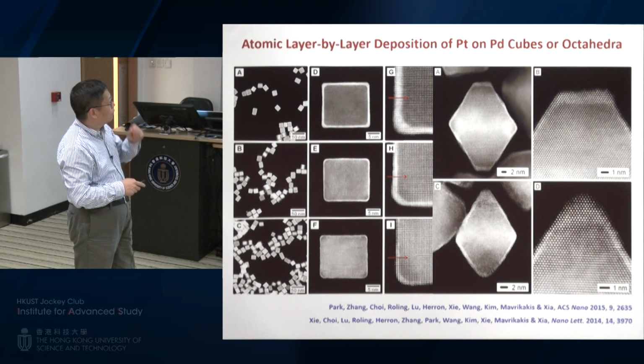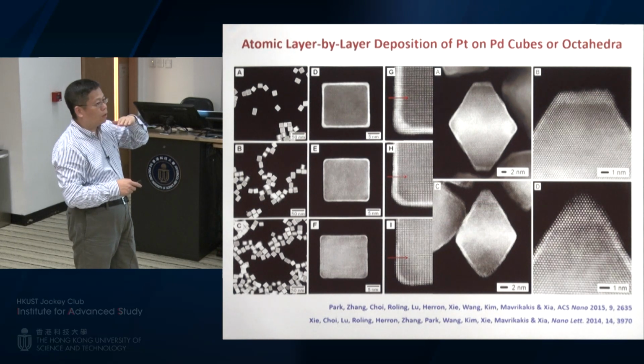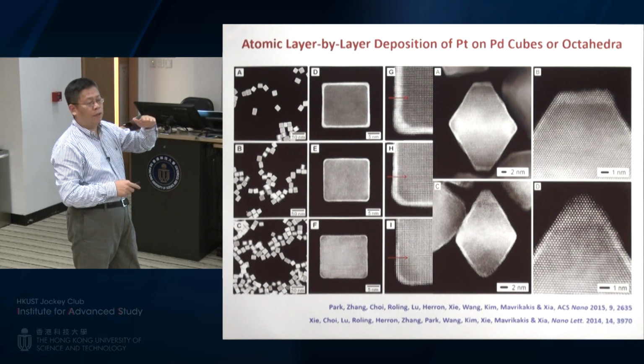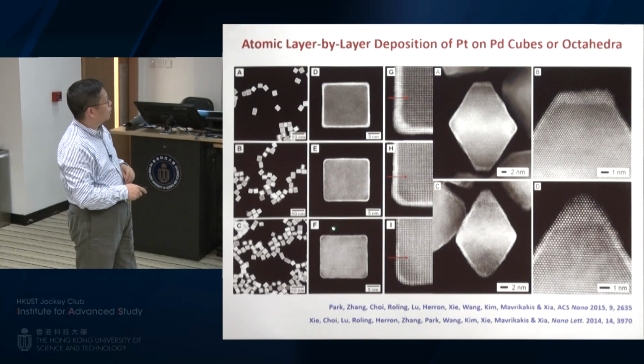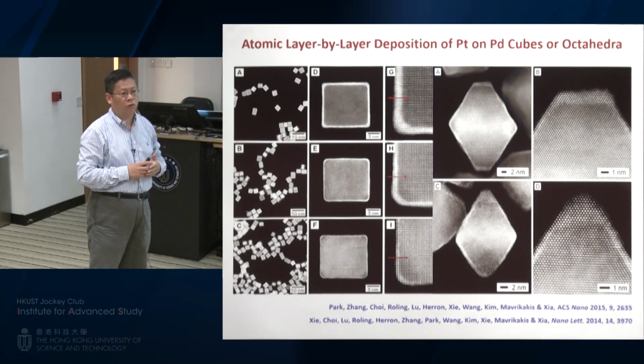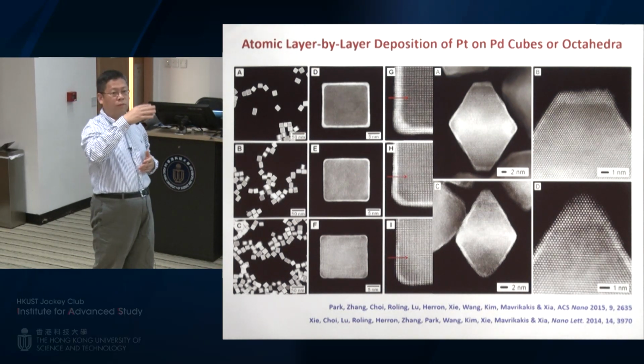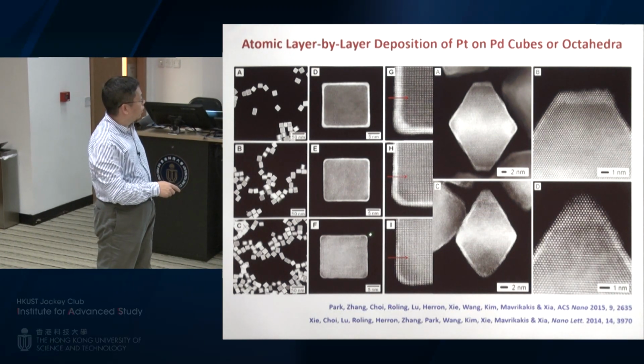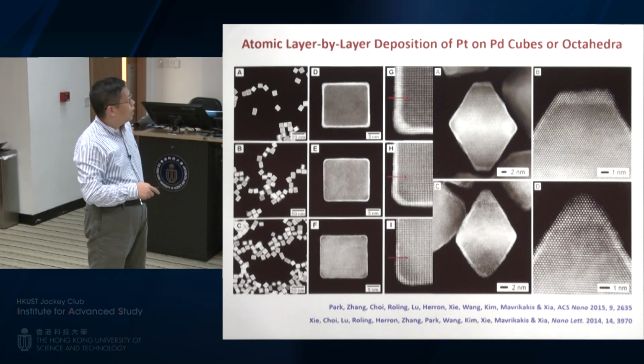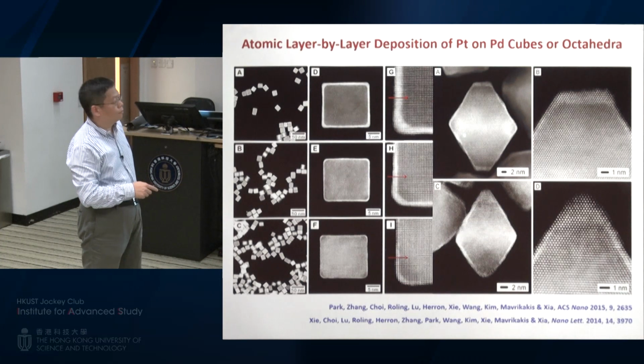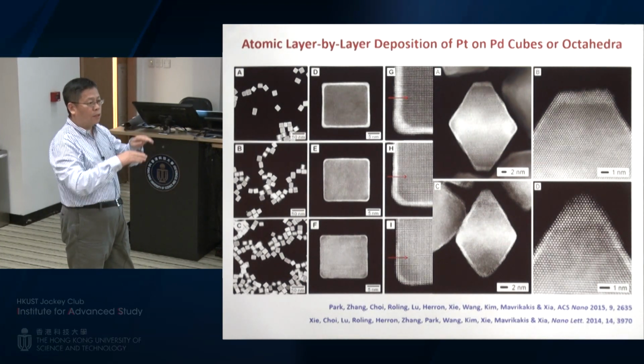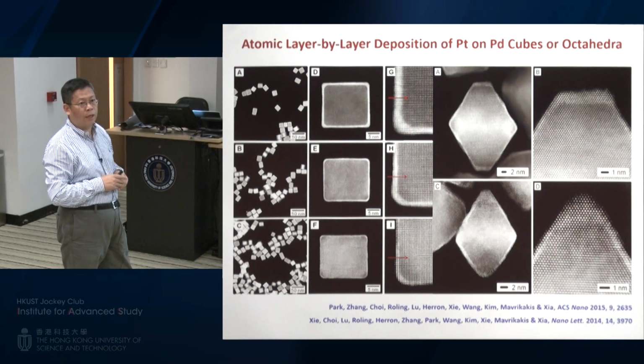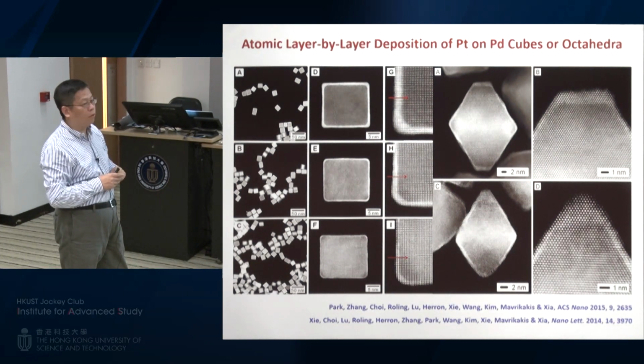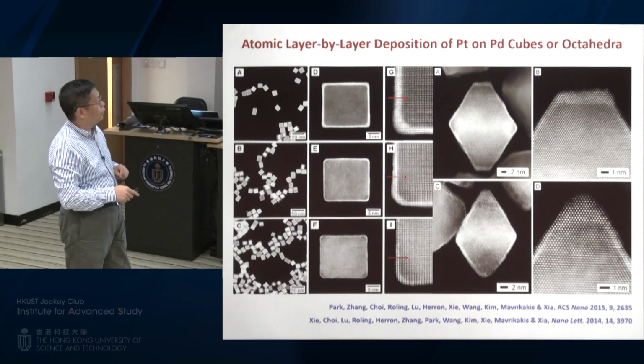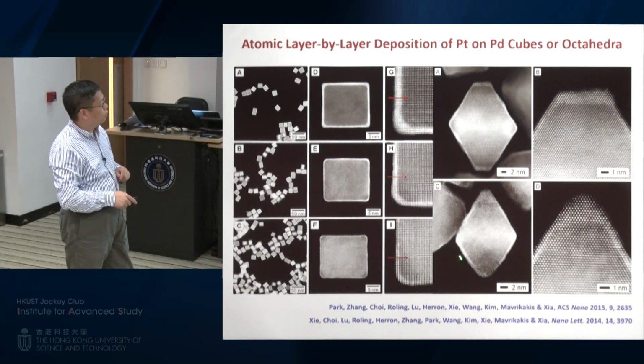And for atom diffusion, as we know, depending on the surface structure, they may have different diffusion barriers. So for cubic systems, in general, you have to use very high temperature, almost 230 degrees, in order to overcome the diffusion barrier to spread the atoms across the entire surface. If you switch to octahedral templates, because the 111 facet is smoother compared to the 100 facet, you are going to have a smaller barrier to the diffusion of atoms. And you can even lower the temperature to like 90 degrees. You can also generate these core shell structures, but with much lower temperature.